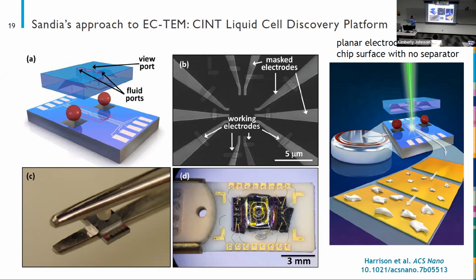After we do that, we put the two chips together. They each have a silicon nitride window that align. That silicon nitride window is very thin and allows the TEM beam to go through the cell so that we can image while we're doing the electrochemistry. We epoxy seal these two chips together. Then we take them into a glove box, fill the cell with electrolyte, and we epoxy and tape over those holes, which were the fill ports. Then we wire bond this whole chip to a chip carrier, put it into a TEM holder, take it into the TEM, hook it up to a potentiostat, do electrochemistry, and then we can image as we're actually doing that electrochemistry.